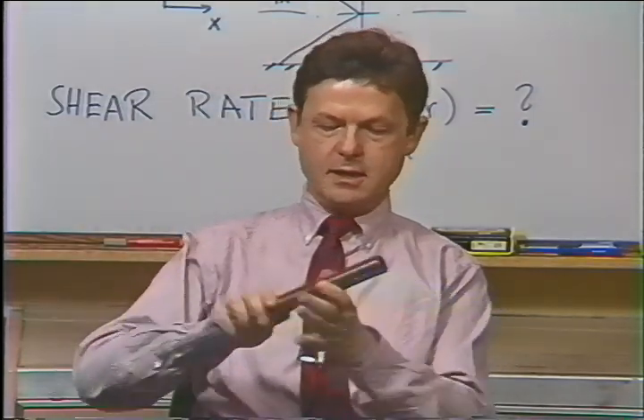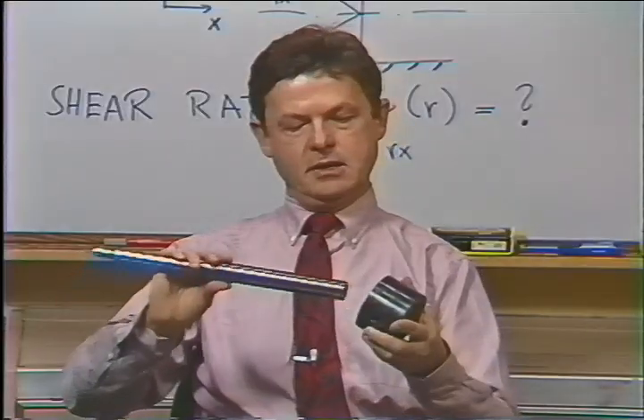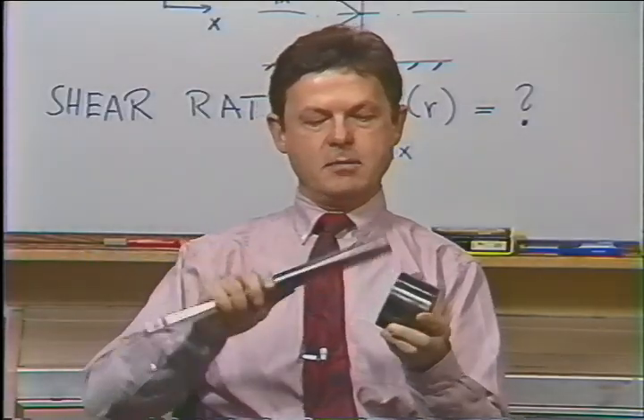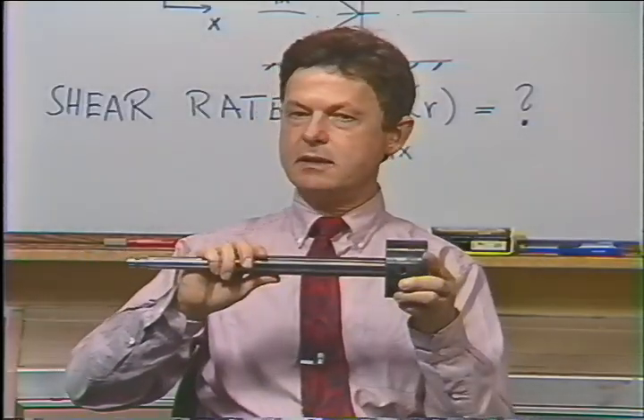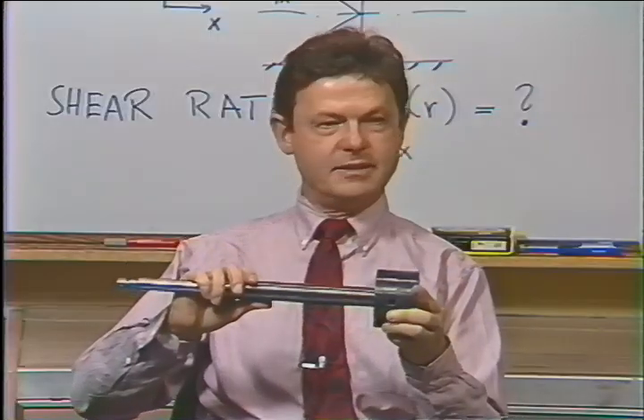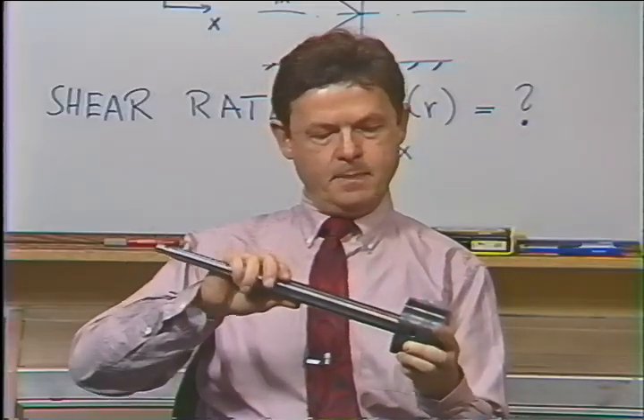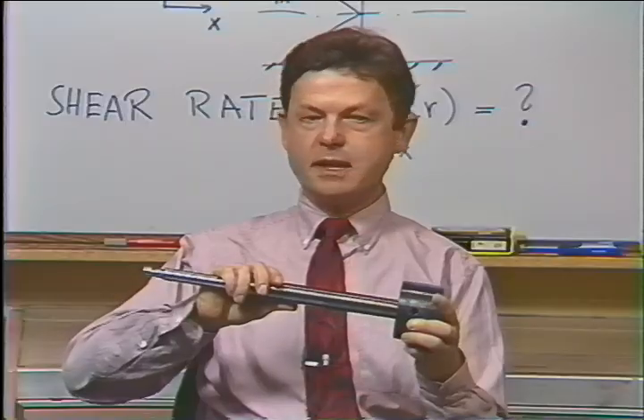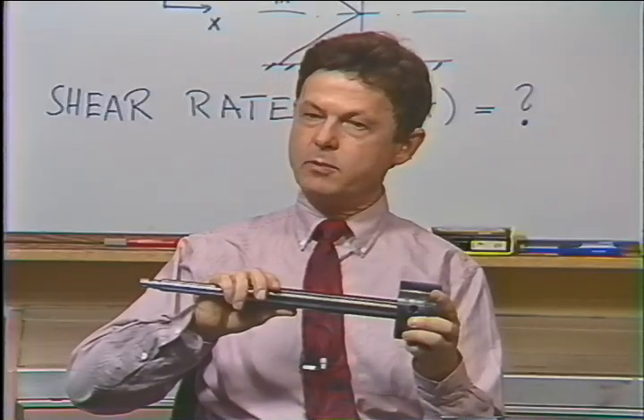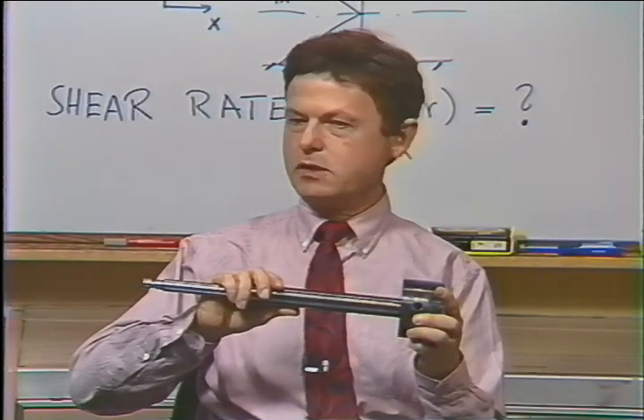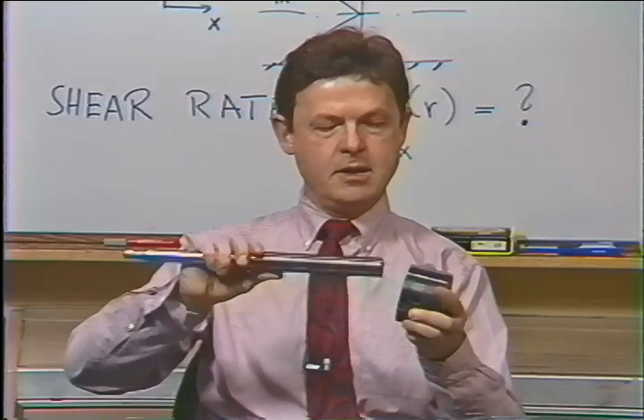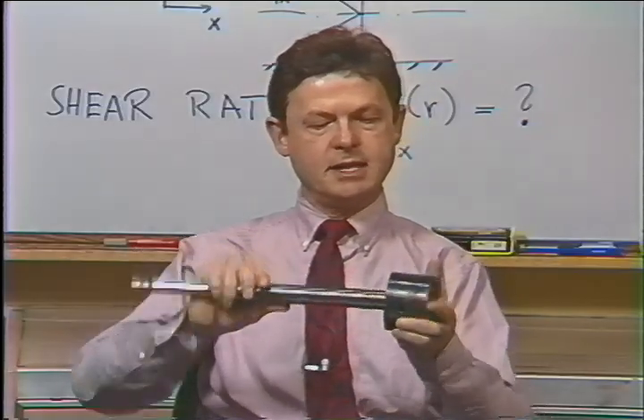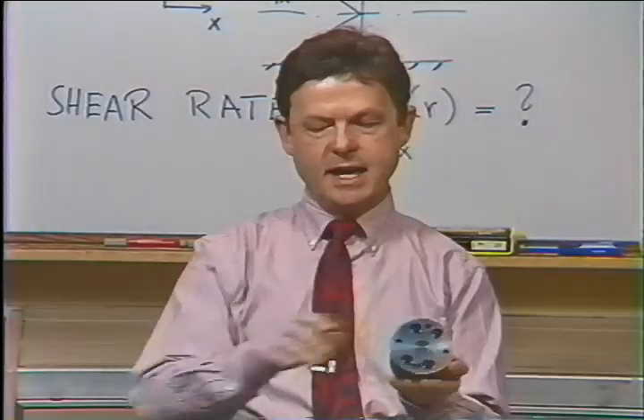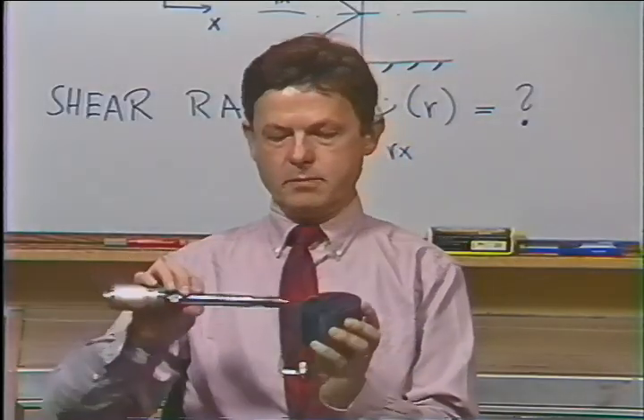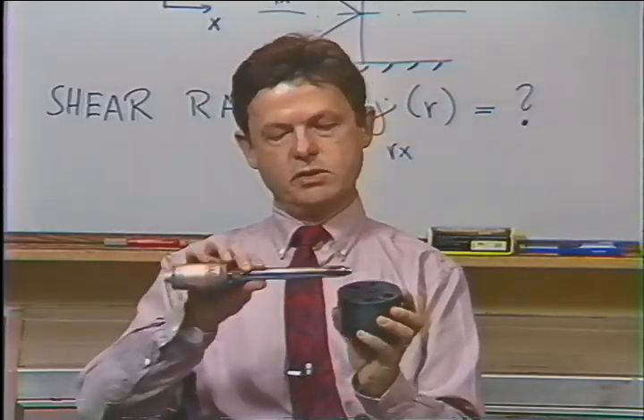Now this capillary then is mounted to the die. Normally there's a metal-to-metal fit between the capillary and the die. It has to be nicely aligned, but then there's no leakage if you work with polymeric melts. If you work with solutions, you would put an O-ring or so in between. But for melts, it's just metal-to-metal contact. This is the die, and the die has holes in which we would mount the pressure transducer.